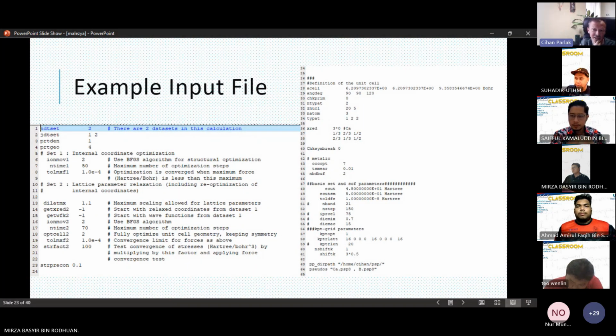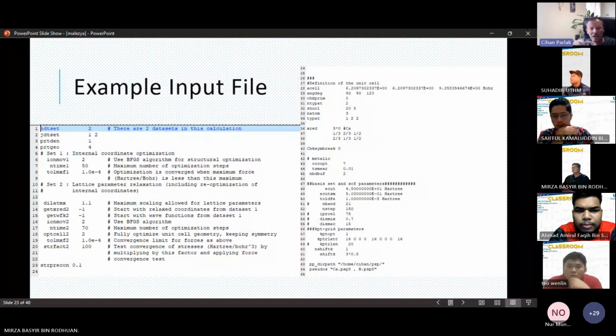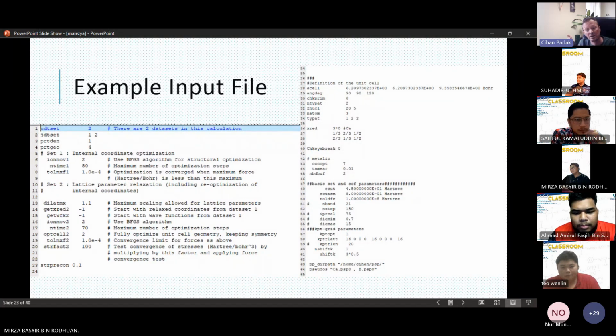The other sections come from the DFT convergence: the cutoff energy, meaning how long or short we take the plane wave expansion. If you make the energy cutoff more than 40 Hartree, accuracy is better, but CPU time is very expensive. We have to optimize that. I will show you in the next slide, I hope. At the bottom of this input file, we give the pseudopotential information. You need calcium and boron pseudopotentials. As I said, I use the pseudopotentials downloaded from PseudoDojo. Okay, next slide, please.